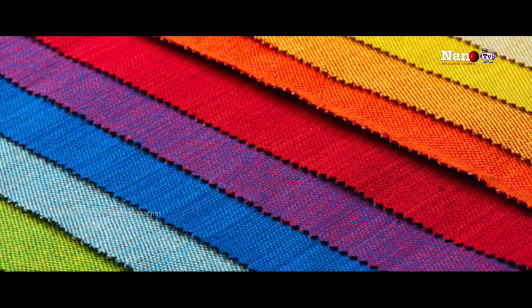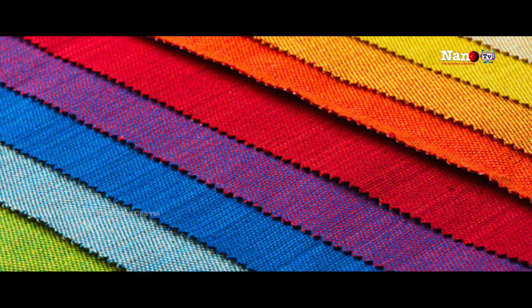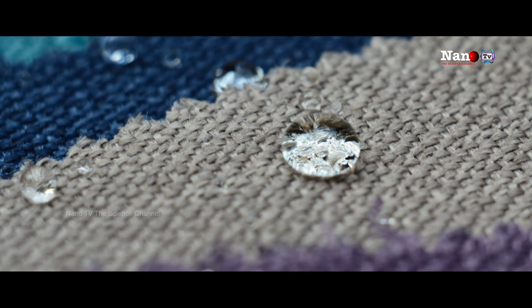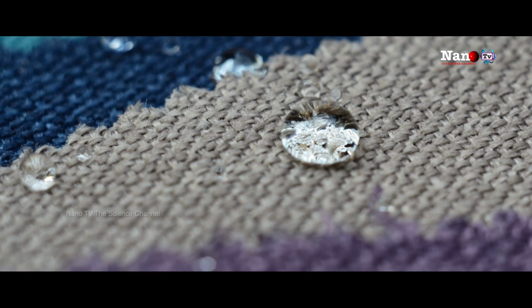Then we don't use the color part for our advantage, but the particle size part, which is very small and gives a very high active surface area, and that we put on textile fabrics and showcase that it gives beautiful properties in terms of antibacterial action, because a metal like silver kills bacteria, that is a very well known process. But when it's in nanoparticle size, it gives excellent antibacterial killing without needing much material. So for textiles coated with nano silver, less than 1 weight%, you don't even know how much silver is there when you take the fabric, and then that silver gives a lot of applications.